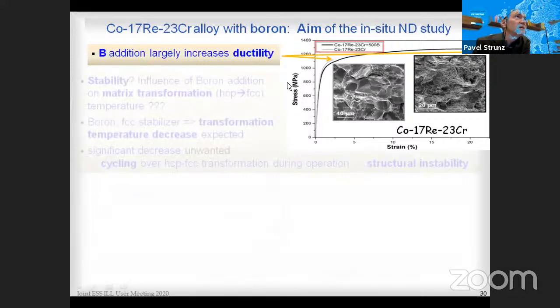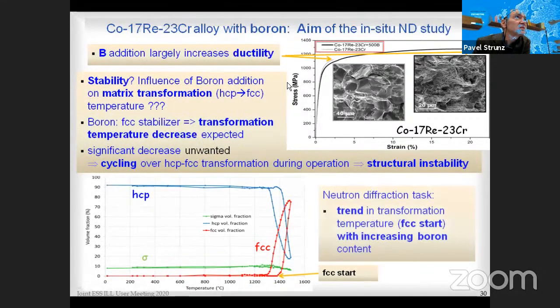It's good. But we also have to care about stability, because we know that boron is an FCC stabilizer, which can shift the HCP to FCC transformation temperature to lower values. If the decrease is significant, it is a problem, because we would cycle over the HCP-FCC transformation during operation. It can bring structural instability. So the neutron diffraction task was to determine the trend in the transformation temperature, this FCC start, with increasing boron content.